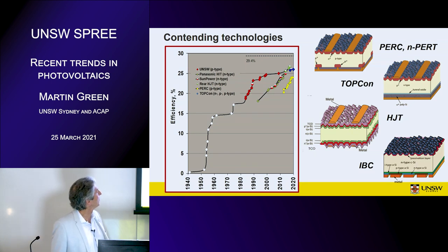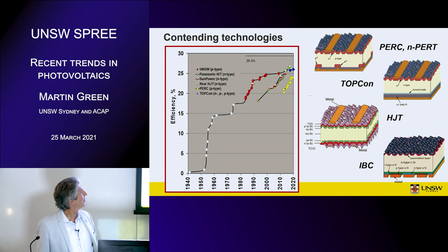So most of them over 25% have been the rear junction approaches, although with the TOPCon now in small cells it has got up to 26%, interestingly with a P-type substrate rather than the N-type. Also with an inverted structure with the junction on the rear of the device, so that it uses the same polarity contacting as for the N-type wafers, but just has the contact on the back.